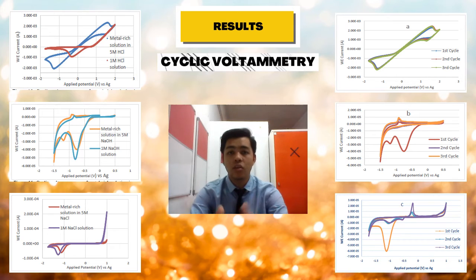In contrast, compared to hydrochloric acid and sodium hydroxide, the metal-rich solution in 5 molar sodium chloride and its background have an identical cyclic voltammogram pattern, as shown in the graph below left. After 0.5 volt, no peak was observed, which can be deduced as no oxidation happening within these two solutions. The reduction peak happened for both solutions, which proved that the reduction process solely comes from the background.